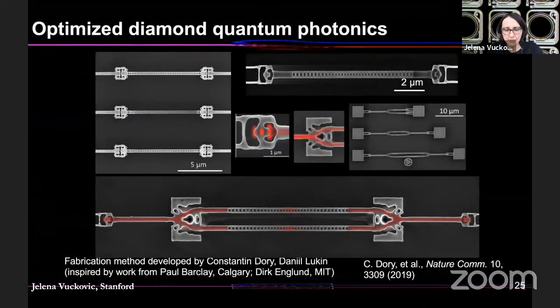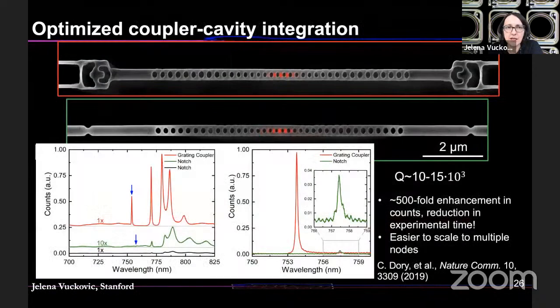So now going back to quantum optics and the work that we do, we can apply this approach to diamond and silicon carbide. Here you see a variety of interestingly looking devices that we designed and fabricated in diamond. They significantly improve behavior of the device without increasing the footprint. For example, the simplest function would be coupler, vertical coupler in the direction perpendicular to chip, free space coupler. We can design it to be much better than these notch couplers that couple only 1 to 2% light that people often use.